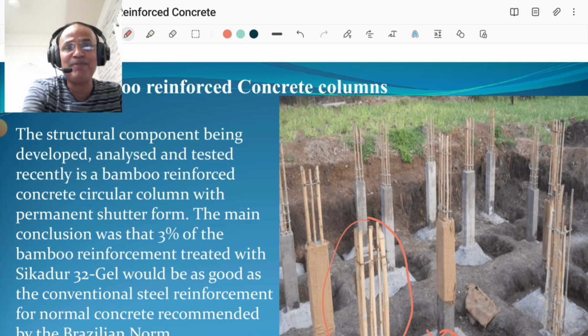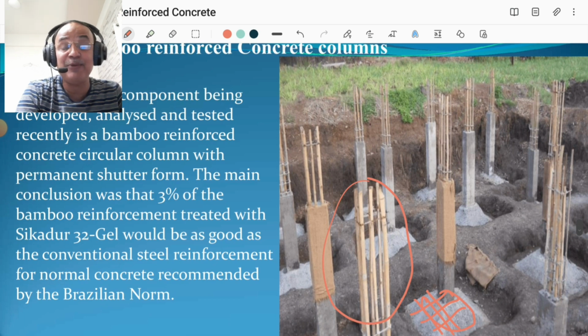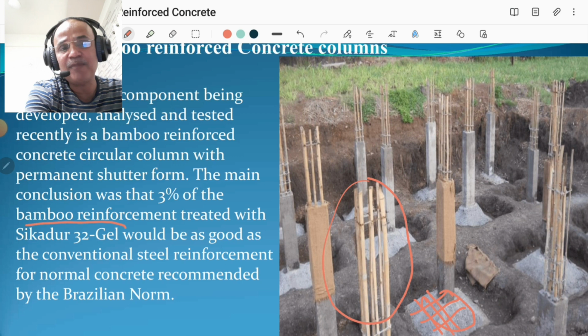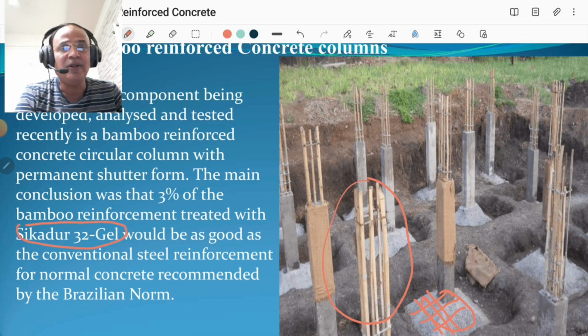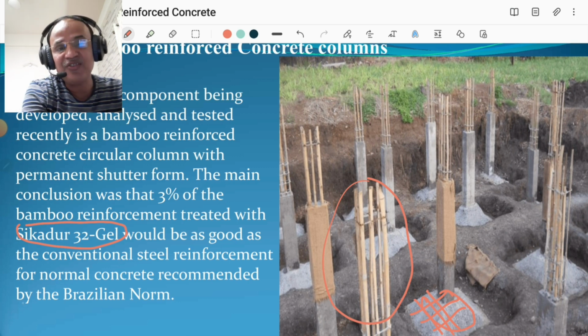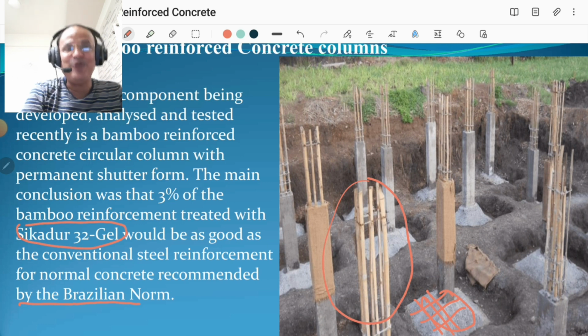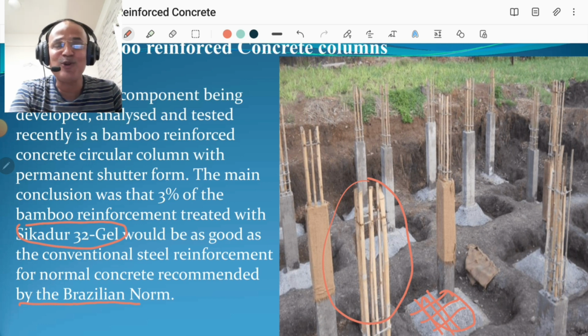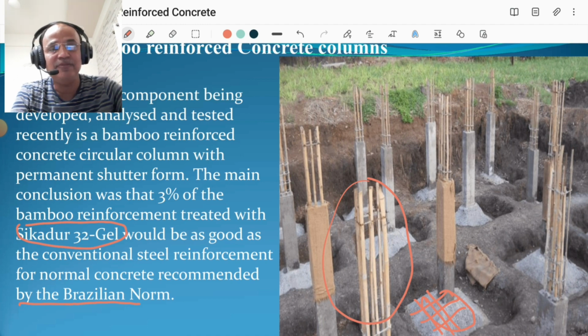The main conclusion was that 3% of bamboo reinforcement treated with Sikadur 32 gel, a particular waterproofing compound or gel, would be as good as the conventional steel reinforcement for normal concrete recommended by the Brazilian norm. So we can use bamboo reinforcement with certain waterproofing material and the strength is as good as steel reinforcement for column sections, and that is a very important finding by that Brazilian team.